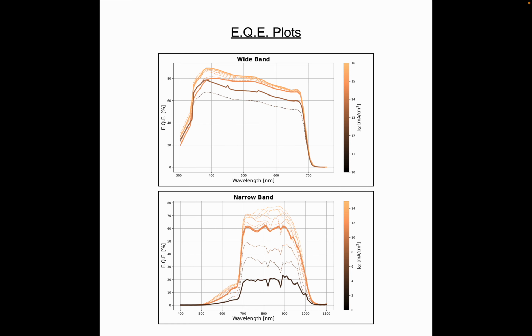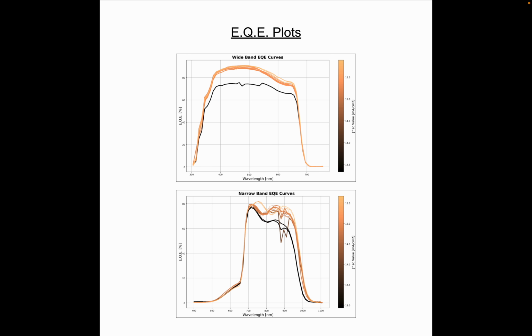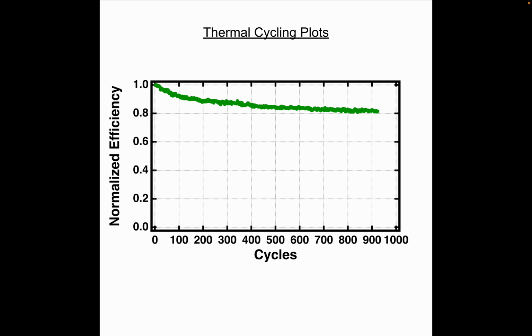So essentially, when you're looking at EQE, JSC, or short circuit current, similar to open circuit voltage like we discussed, it's a big measure of efficiency internally. And so both cells had done pretty good in both layers. However, in the narrow bandgap, we can see lower JSCs, and specifically our bold lines, or our post-thermal cycled cells, the ones we did those temperature fluctuations on, showing that damage. And so we were able to actually improve those cells and do some updated batch findings where we had both strong JSC values at some of the highest standards we've ever been able to see for space-based considerations.